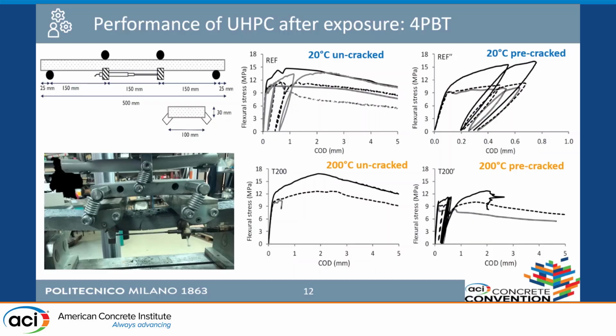We performed flexural tests. You see that the samples are a little bit different from what is shown in the standard, because we are dealing with thin beams. This is a typical test that we perform in Milan. Just to focus here, you see that on the left we have the response after the thermal treatment for specimens that have not been cracked before. On the right, we have the behavior of the specimens that have been pre-cracked before the thermal treatment.